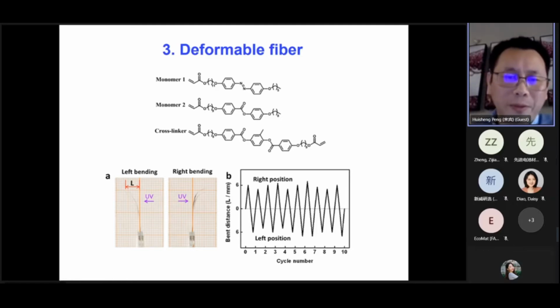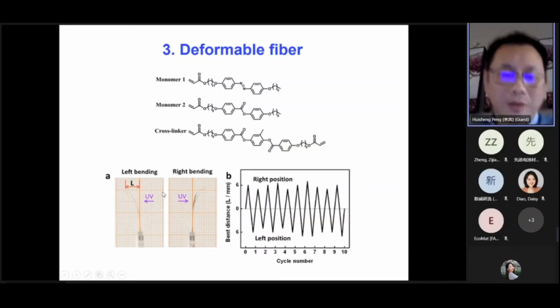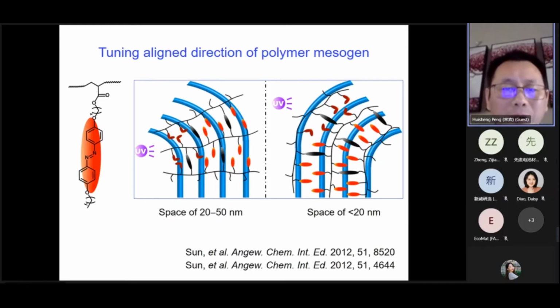They can change shape. We designed the monomer with azobenzene, and you know it can go through a trans to cis transition. During this process, the length of this unit will change by about 2.5 angstrom. If these monomers are polymerized and oriented together, macroscopically we will observe the shape change. This scheme shows the molecules inducing the shape change by UV light. Many researchers work on this, but our focus is to control the direction of the shape change by simply tuning the spacing of the aligned carbon nanotubes.